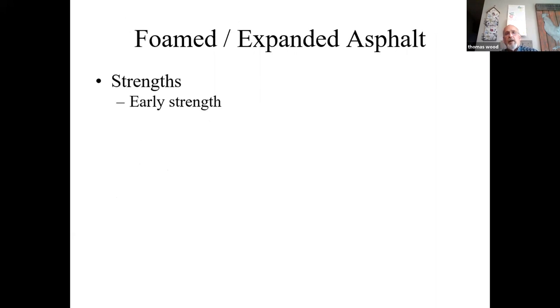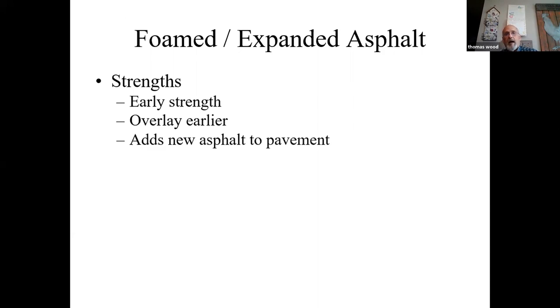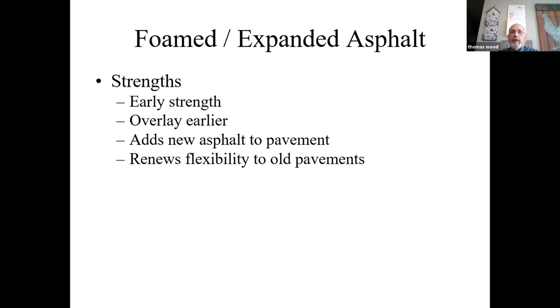The strength of foamed asphalt or expanded asphalt is early strength. They claim you can overlay it earlier. I'm not totally convinced on that. It adds new asphalt to the pavement. And what we're trying to do when we do in-place recycling is take an old pavement and add the proper amount of new asphalt to restore the crack resistance, but not add so much asphalt that we make it prone to rutting. And that applies whether it's emulsion or foamed or expanded asphalt.